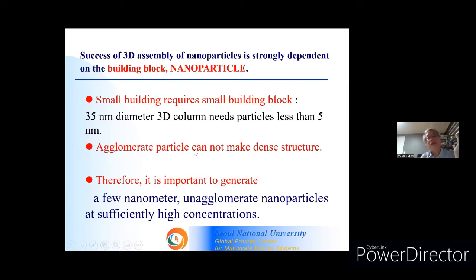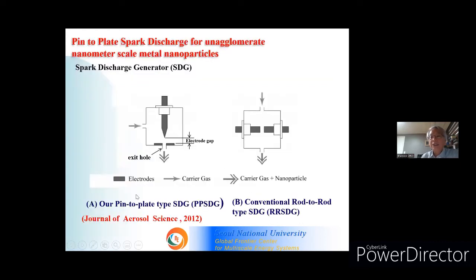And agglomerated particles cannot make a dense structure. Of course, depending on your application, you may prefer to use agglomerated particles, for example in some catalytic applications. But if you want to make dense nano building, then you need to generate few nanometer unagglomerated nanoparticles at sufficiently high concentration. To achieve this, we developed a new spark discharge generator.